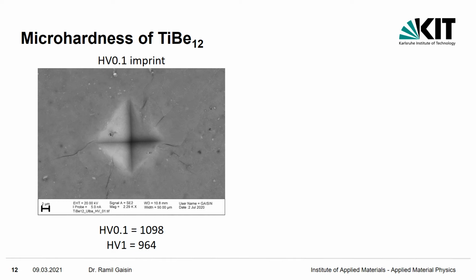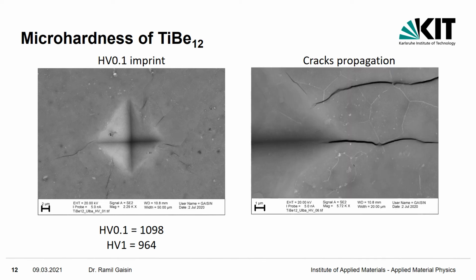Titanium beryllide is a very hard material with about 1000 in Vickers. There are many cracks extending from the impression. They propagate both along grain boundaries and within grains. Using this equation and knowing the force, the crack length, elasticity modulus, and hardness, the fracture toughness was estimated at 2.4 megapascal square root meter. This value is common to many brittle materials such as intermetallics or ceramics.